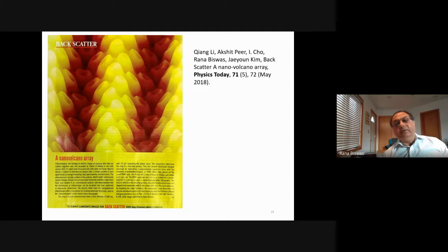And I don't want to elaborate on many of these details here, but this was highlighted in Physics Today that year. And what we did, we took that PDMS charged nanocup array and we used the PDMS to transfer the pattern into a photopolymer. And here you're looking at the photopolymer, which also had a secondary pattern, these stripes that were created by laser interference lithography. And the secondary pattern had a pitch of 2.5 micron, whereas these nanocups had the same pitch, 750 nanometer.